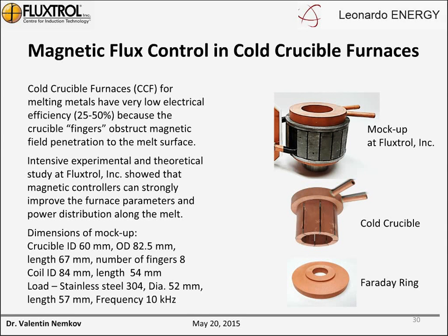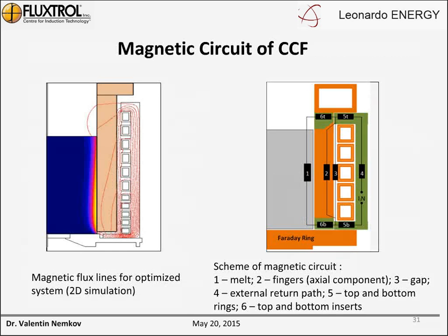Intense experiments and theoretical studies show that magnetic controllers can strongly improve the furnace parameters and power distribution along the melt. And we made a prototype mock-up and made tests at a frequency of 10 kilohertz. Here is a magnetic circuit for a cold crucible furnace. On the right side, you can see the circuit, which is more complicated than what I showed you before.